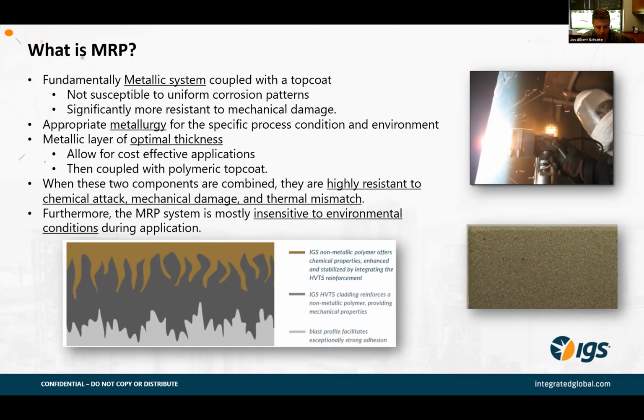Since it's a metallic system, the metallurgy can be selected very specifically for the process environment. The metallic layer can also be optimized to give you the best protection, but also economic and cost-effective protection. When this metallic layer is coupled with a polymeric top coat, you get a protective layer that's highly resistant to chemical attack, mechanical damage, or even thermal mismatch. Furthermore, because it's a metallic base, the system is not sensitive to all those environmental controls necessary for typical organic applications.